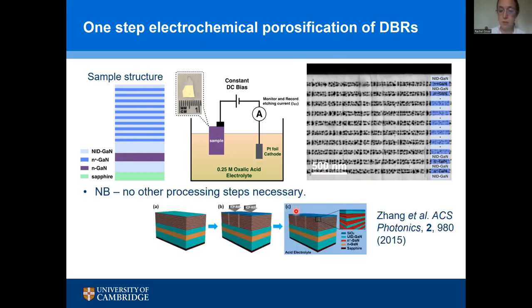This idea, as far as I'm concerned, came out of a group at Yale, and their process is illustrated now at the bottom of the slide. So they start off again with one of these doped, undoped stacks. They then cover it in silicon dioxide, pattern the silicon dioxide into stripes. So windows with and without silicon dioxide in stripes across the surface. Use a deep reactive ion etch to create troughs or trenches in the material, and then the etchant accesses those doped layers from the side, from within these trenches.